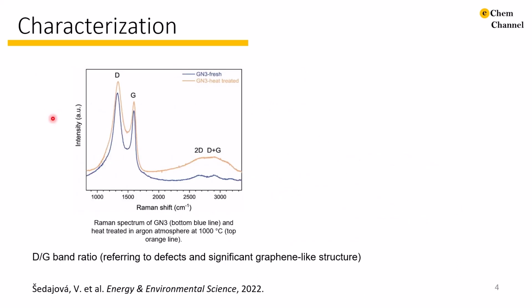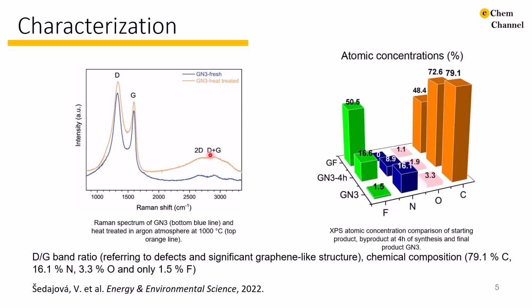Next, we did the characterization of our material. The Raman spectrum is showing a large presence of sp3 carbons, including the non-healable defects and the vacancies, and also a fair number of aromatic areas. Following, the atomic concentrations of the GN3 final product consist of 16 atomic percent of nitrogen, only 1.5 atomic percent of fluorine, and 79 atomic percent of carbon.